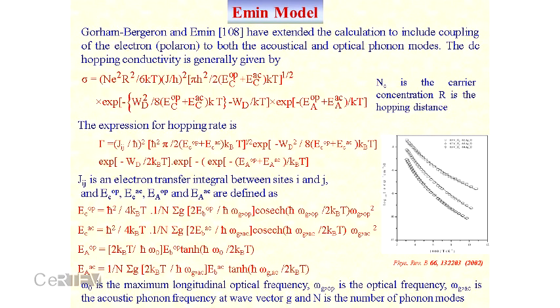And I just like to mention that if we simulate these results in a different way, then we have seen that this is the best model to describe the electronic motion in semiconductors for the entire range. In Mott's model, we have to consider two models. One is the phonon-assisted model at high temperature. One is the tunneling model at low temperature. But here, we have considered the hopping throughout the whole range. We have taken into account all the possible combinations of phonons, either longitudinal, optical, or acoustic phonons. So we published this a long time back, of course.